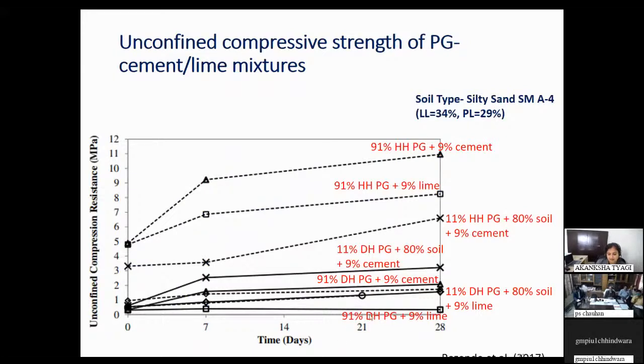And the thing is, they found that for two types of phosphogypsum, dihydrate and hemihydrate, the dihydrate phosphogypsum has less strength when added to a soil or with any kind of admixture like lime or cement, while hemihydrate phosphogypsum, which is CaSO4·0.5H2O, has very, very high strength.